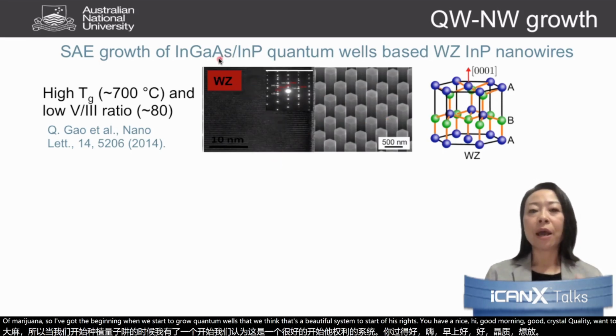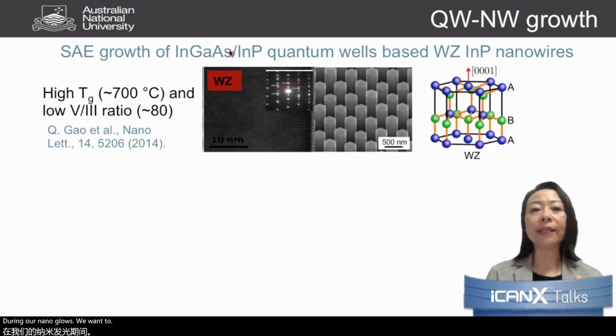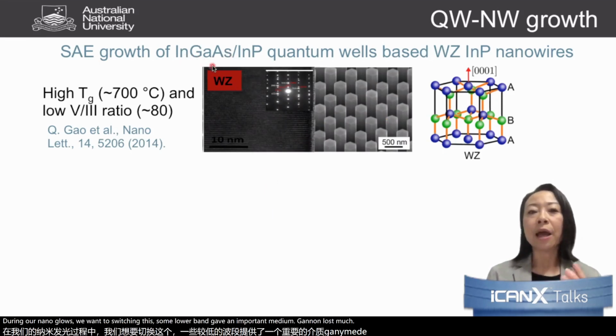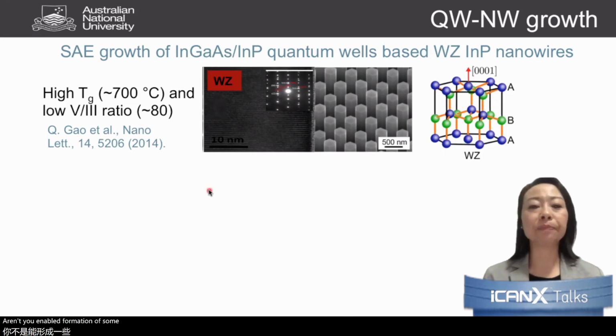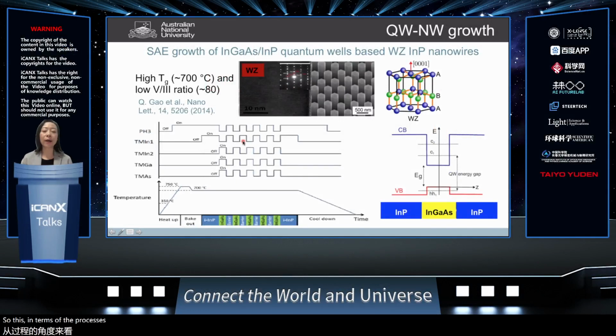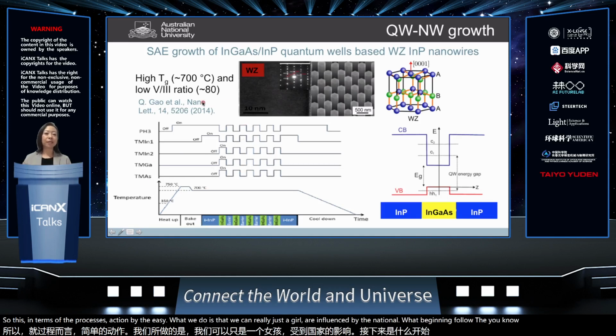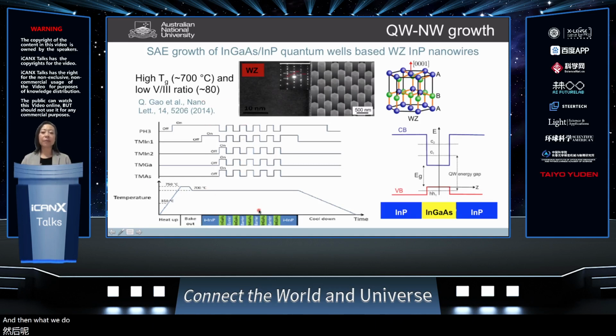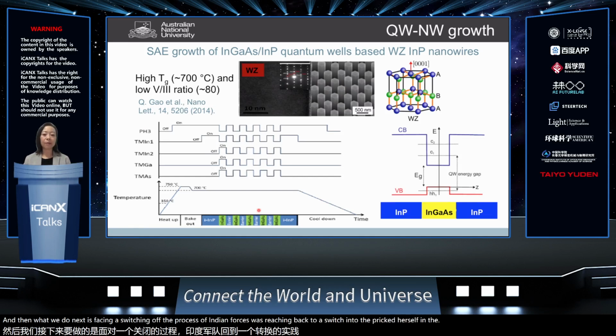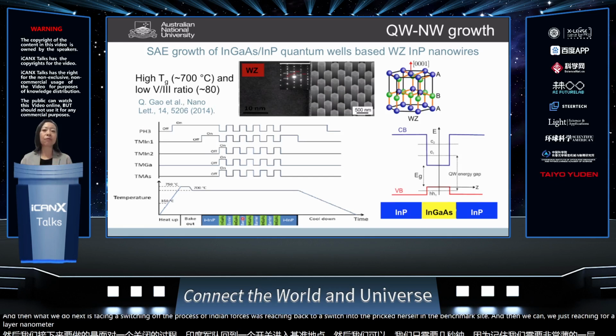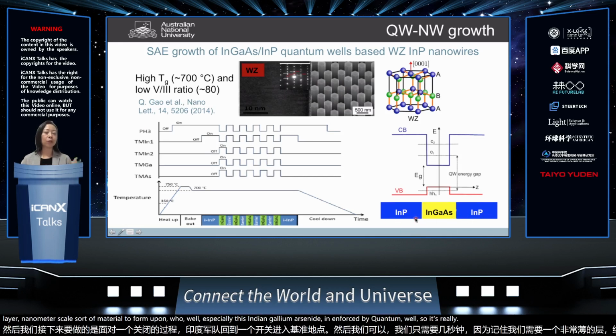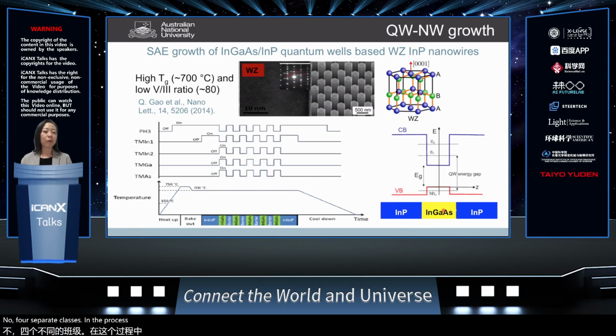During our nanowire growth, we want to switch in this lower bandgap indium gallium arsenide to enable the formation of a quantum well. In terms of the process, this is actually quite easy. We just grow our indium phosphide nanowire at the beginning, following the recipe we developed in the past. And then we switch off the indium phosphide precursor and switch to the precursor of indium gallium arsenide, just for a few seconds, because remember, we only need a very thin, nanometer-scale layer of material to form a quantum well, especially this indium gallium arsenide, indium phosphide quantum well. So it's really switching precursors back and forth, and we only need a few seconds.